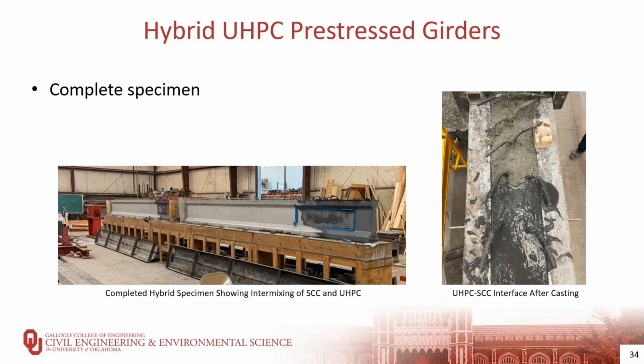The divider then was removed after we finished casting all the way to the top of the girder, and you can see the picture on the right here. It will show the interface after the divider was removed. And then the picture on the left here shows the complete specimen after pre-stress release. And pre-stress release was done 2 days after casting.